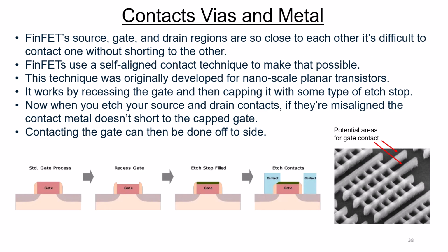Contacts, vias, and metal. FinFETs' source, gate, and drain regions are so close to each other, it's difficult to contact one without shorting to the other. FinFETs use a self-aligned contact technique to make that possible. This technique was originally developed for nanoscale planar transistors. It works by recessing the gate and then capping it with some type of etch stop. Now, when you've etched your source drain contacts, if they're misaligned, the contact metal doesn't short to the capped gate. Contacting the gate can then be done off to the side.